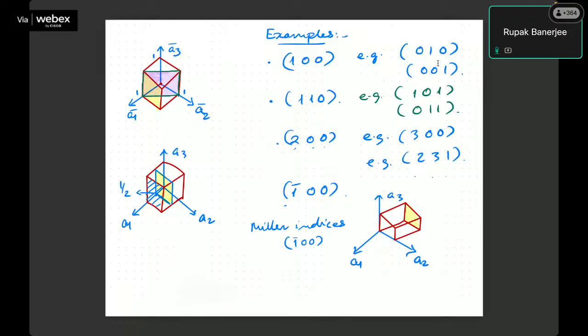Similarly, you can have 010 and 110, which means the plane which is intercepting around a2 or a3, and they are actually parallel to the other axis here. Look at 110. So look at this violet shaded part, which means that the intercept in a1 is also around 1, at a2 is also 1, but this is parallel to the a3 axis. So you have 110, right? Similarly, you can have 101 if it is cutting along two different axes. There's something which is parallel to the a2 axis, or something which is parallel to the a1 axis.